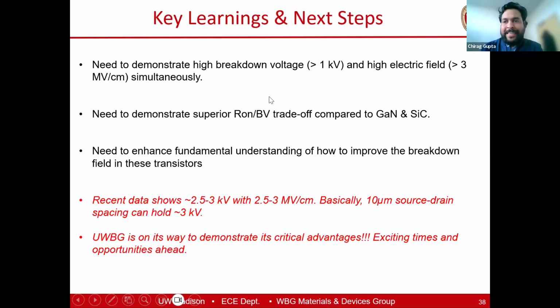But one of the key things I want to highlight is that a few things are still lacking in the ultra wide bandgap space, where we still need to demonstrate high breakdown voltage with high electric field. And when I say high electric field, I'm not talking about 10 megavolt per centimeter or 8 megavolt per centimeter. Just crossing gallium nitride or silicon carbide, basically 3 megavolt per centimeter with 2 kilovolts of breakdown voltage, itself has proven challenging in lateral devices, in GaN and even gallium oxide based lateral devices.